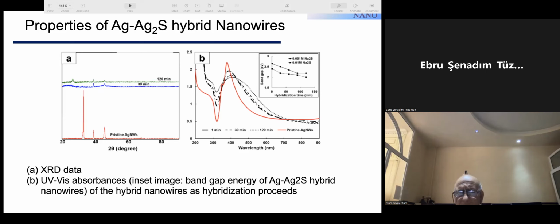And on the right part, we showed the dependence of absorption spectra on wavelength. And here we showed the dependence of the band gap of the resulting silver sulfide structure on hybridization time. And as we can see from this figure, depending on the hybridization time of surface modification of silver nanowires, the band gap of the structure was decreased.